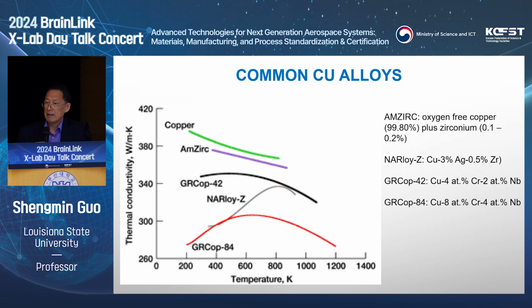at elevated temperatures. We all know the melting point for copper is around 1000 degrees C. Apparently, nobody can operate there because when you get there, the thing will melt, right? The pure copper, when you heat it up, will become very soft and will not be able to sustain the high pressure inside the combustor.